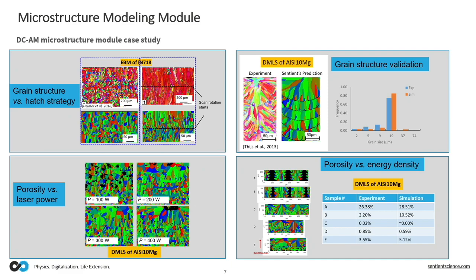In the lower part, again, as I mentioned in the previous slide, I'm showing the responsiveness of the model in predicting the porosity when I'm changing my process parameters. Of course, the machine OEM provides a default optimum set of parameters that, if you use that, you get the best microstructure. But then what happens when we deviate from those for any reason? And again, you can see the comparison in the lower right-hand side, the prediction of our model versus experimental builds of those aluminum silicon alloy parts, and how close, or in some cases not that close, it is compared to those experimental porosities.